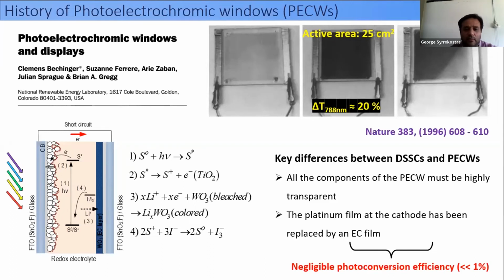Therefore, there are two key differences between the dye-sensitized solar cells and the photoelectrochromic windows. First, in the case of photoelectrochromic windows, all the components must be highly transparent. Therefore, the utilization of solar light is not so efficient. And also, the platinum film at the cathode is missing, meaning that the reduction of triiodide ions is not so efficient. And for both of these reasons, the photoconversion efficiency of these devices, at least initially, was negligible.